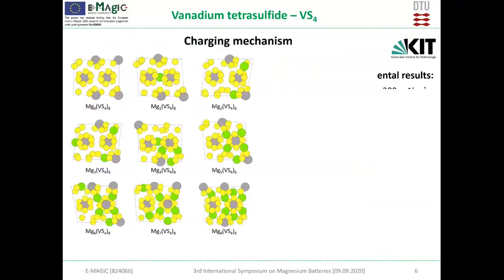So we were doing this, just putting magnesium atoms in random places, trying to find the most optimal place where magnesium will sit. And we are doing this for many random configurations to find out which structure will be the most stable. And here I'm presenting the structures that got the lowest energy. What is interesting here is that when we put extra magnesium into the structure, it always goes to the place close to magnesium already. So the magnesium is not uniformly located in the entire cell. It's always just close to each other.